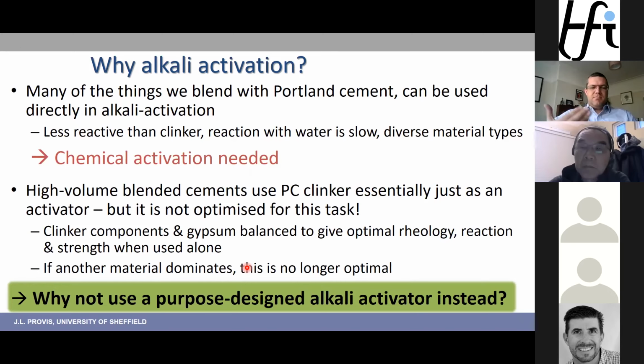Portland cement is, as I mentioned, a blend of 5 minerals. It's clinker minerals and gypsum, blended, balanced and ground to give optimal rheology, reaction processes, and strength development when it's used by itself as a cement. If we're just using that as a way to trigger the reaction of another component, it's not optimal. It's not the best use of this cement that we've spent all our CO2 making. So we're not using our cement optimally, and we're also not using our supplementary powders optimally.